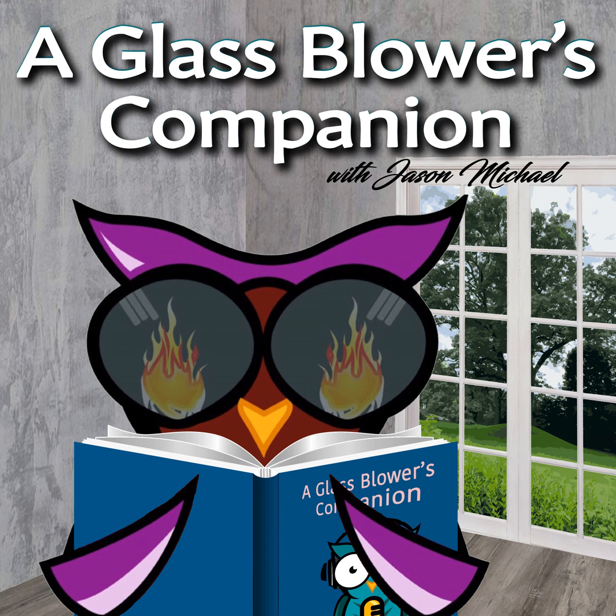And for color to be compatible, the color has to have a very, very similar cooling rate. I'm pretty sure most color now is fine-tuned to where it's almost exactly the same as borosilicate. But when I first started, there was a jade green going around, and whatever chemistry it takes to create that color in glass, it's not very easy to do. I remember doing perfume bottles and some beads we were making for the Renaissance Festival, where I would do a nice color wrap around the glass, and the next day, after running a nice perfect annealing cycle, you could see that on both sides of the green stripe in a spiral, the glass was cracked all the way around, and it left a texture on the surface where you could rub your hand across it and feel that the green was actually separating itself from the clear, even after running a perfect annealing cycle.